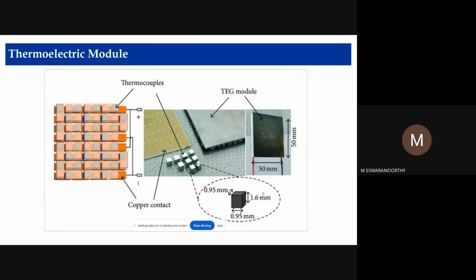So probably someone might know how this thermoelectric module works on this component. It is a fabricated, exploded view of the thermoelectric module and a joint view, showing the size of the thermoelectric leg, which is most important here. It is square in cross section, almost 0.95 mm, and 1.6 mm in height, where breadth and width are 0.95 and only the height is 1.6.